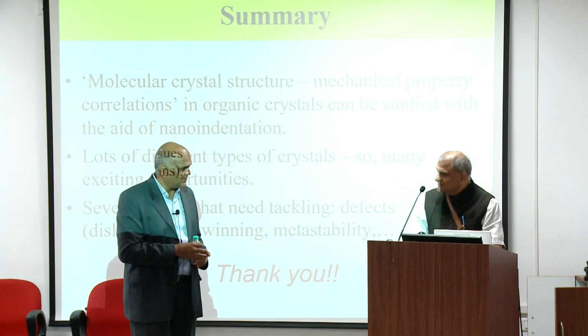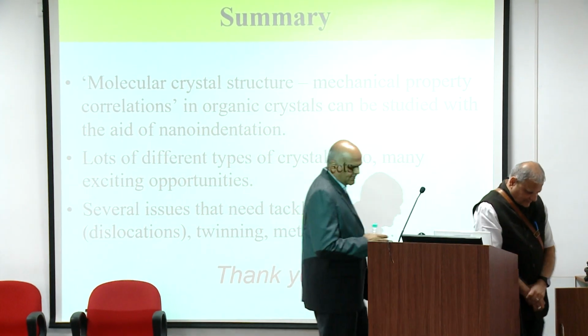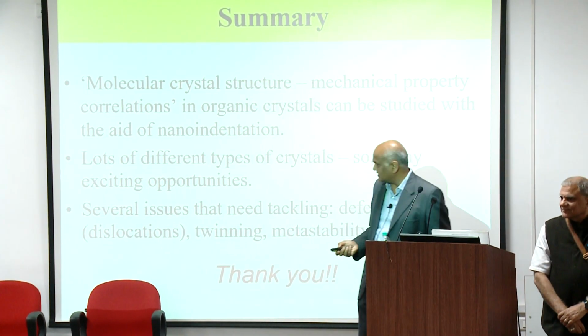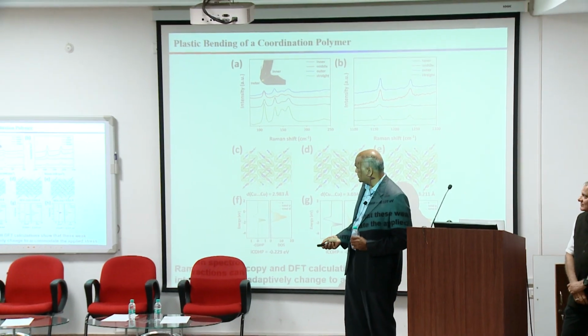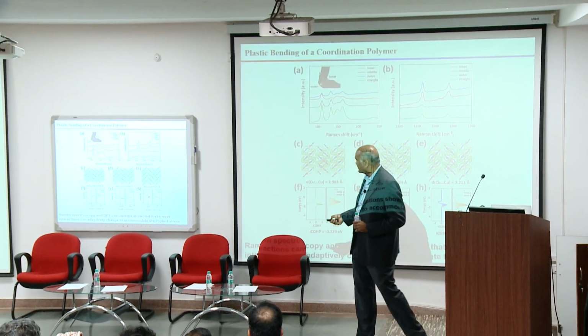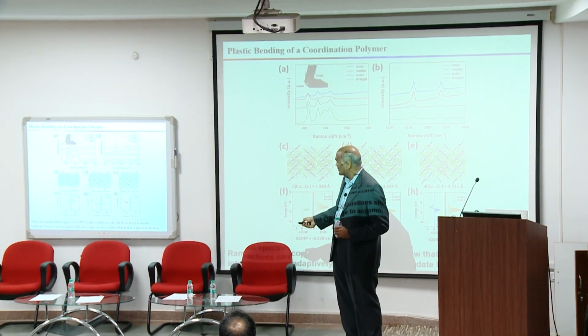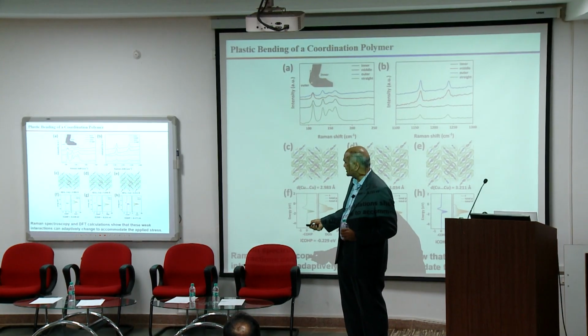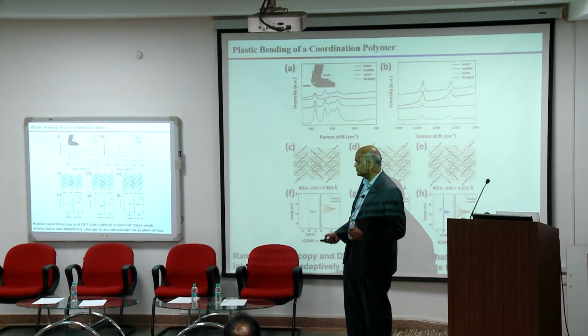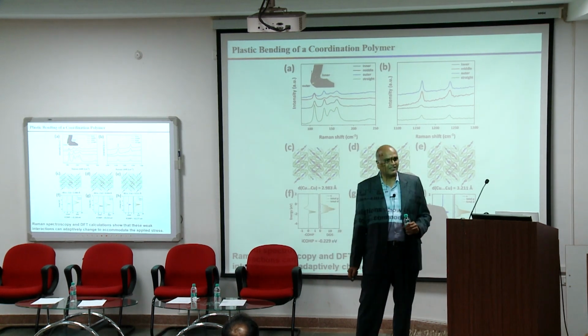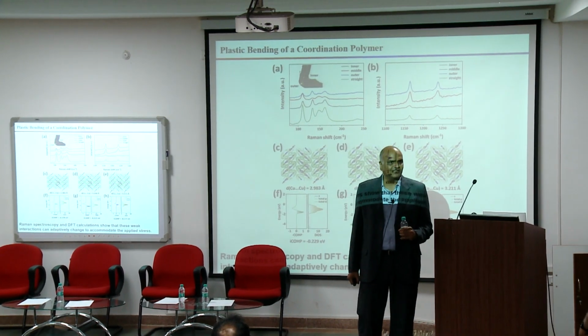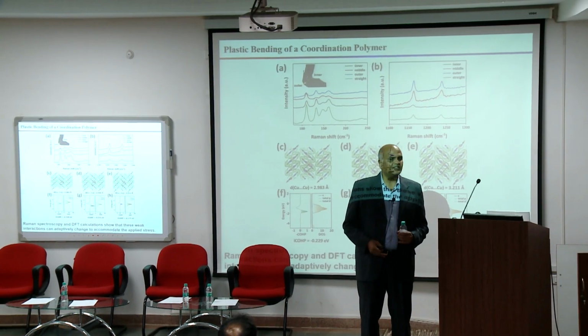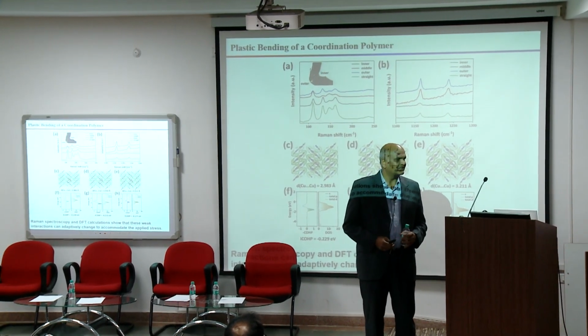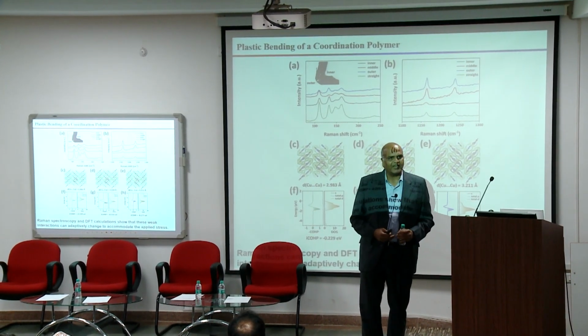If I go back to that slide, I think they have those bond extensions. You see here the copper lengths are 2.983 angstroms to 3.034 and 3.211. So there are those stretches. It's very tiny, but it's a reasonable strain, beyond the standard deviation. These are reasonable strain values that happen.